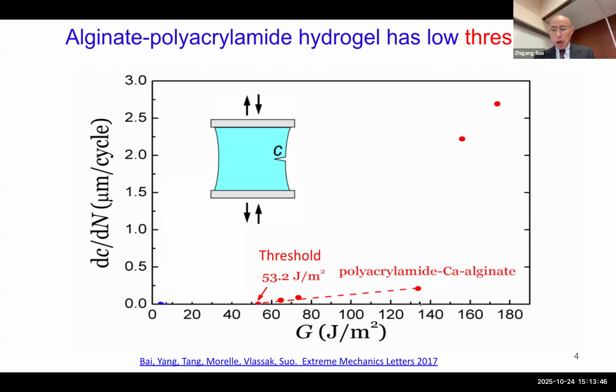Now, you say, okay, you reduce the load. You reduce to about 50 joule per meter squared. We cannot detect crack growth anymore. So this number is called the fatigue threshold. Fatigue threshold is 50. Toughness is 10,000. So a huge difference between these. Of course, in everyday life we have the experience: if you cannot break something one time, you break it many times, maybe not 10,000 times. So fatigue crack growth is very important.